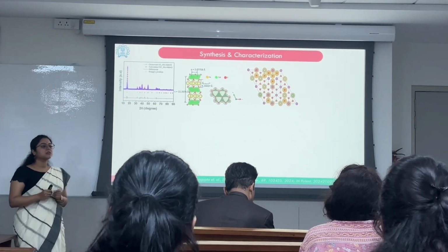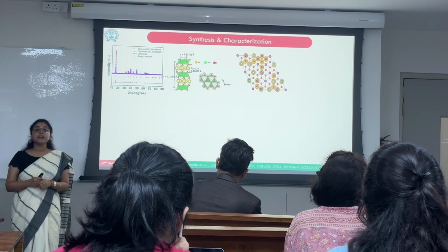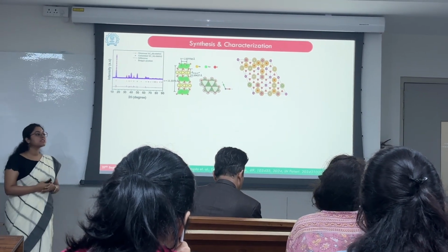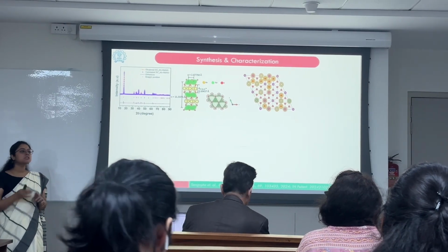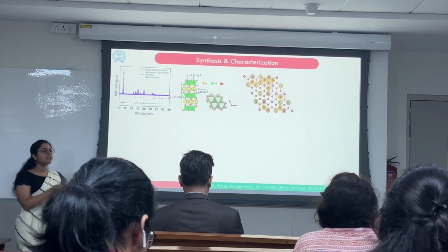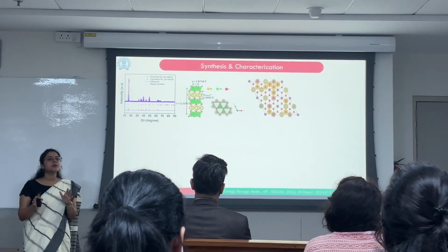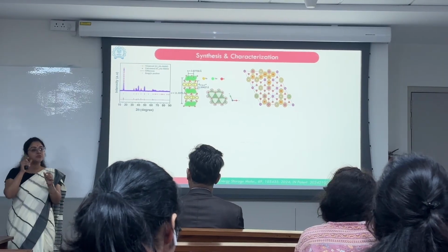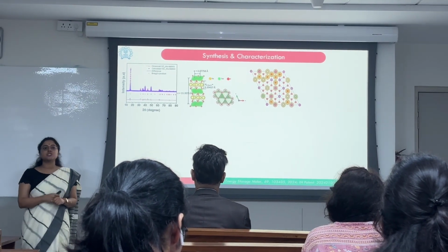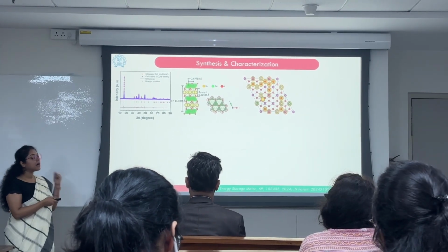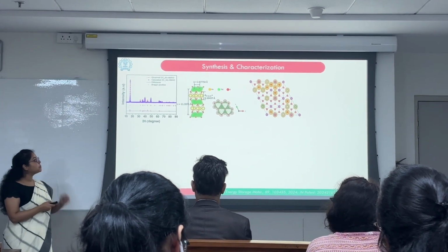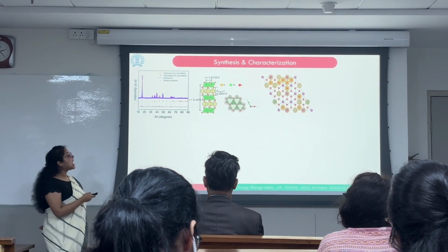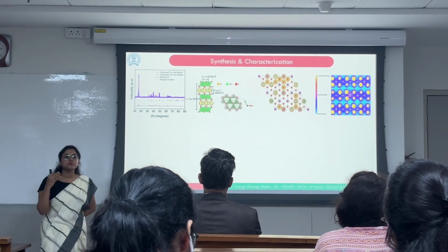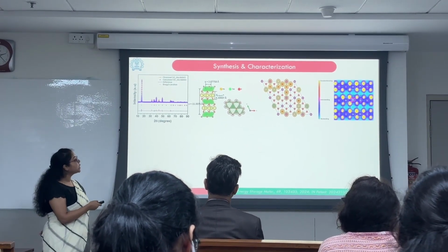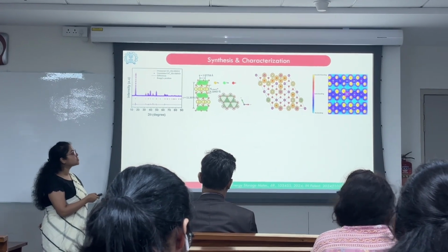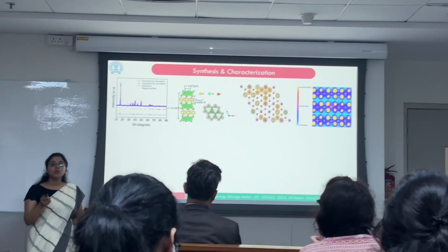Another important factor for the longer cycle life is the sodium-ion diffusion pathway, which we, with the help of Professor Dan Major's group, found out. We considered two pathways. The first case in which the sodium ions are occupying only the edge-shared phases, and the second case, which is a much more practical one, where a sodium ion is sitting in the face-shared space in between two edge-shared voids. In this case, we observe that the pathway diffusion barrier is much lower in comparison to that of the pristine one. And through the electron localization function, we also identify the nature of the bond, which shows that the niobium-oxygen bond is much more ionic in nature, as well as the manganese-oxygen. However, the nickel-oxygen bond is much more polar covalent in nature.